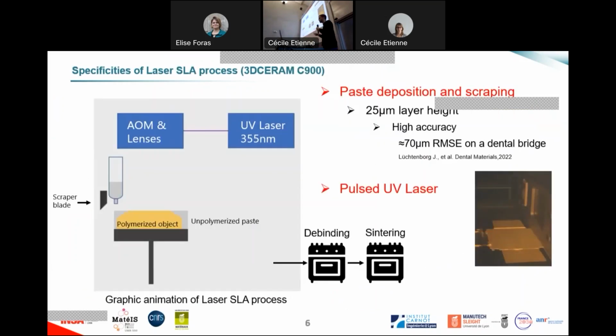So for the presentation of the stereolithography process, here on the left, you can see that at first we add from the syringe some paste to form a new layer. So we add the paste and we scrape it in order to have a very thin but very regular thickness of our layer. And then we can make the polymerization following the pattern that we want to add the new layer. And we do this layer by layer. Then we remove the unpolymerized paste and make the debinding and the sintering step.